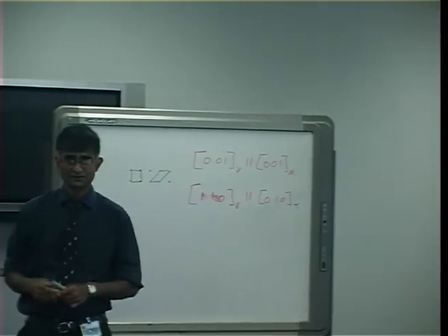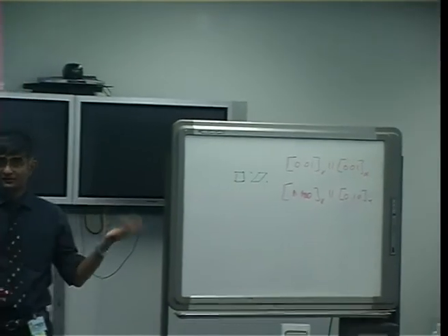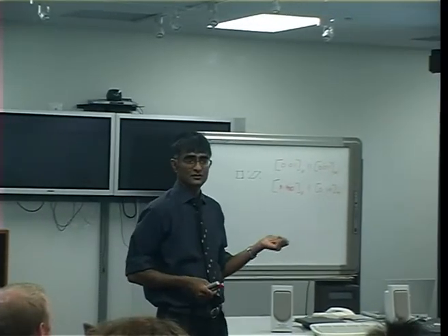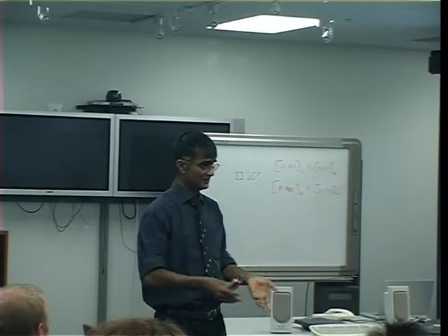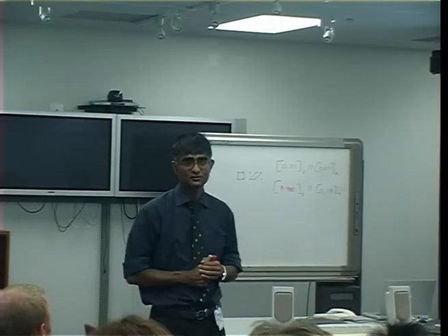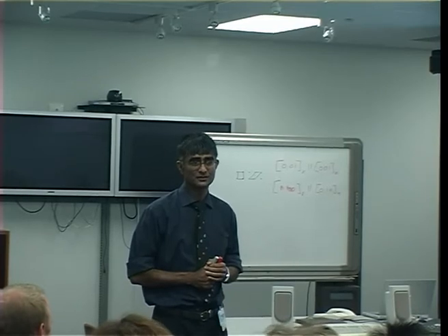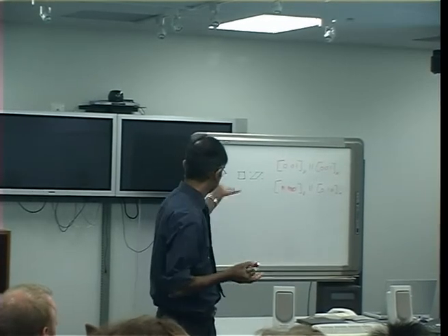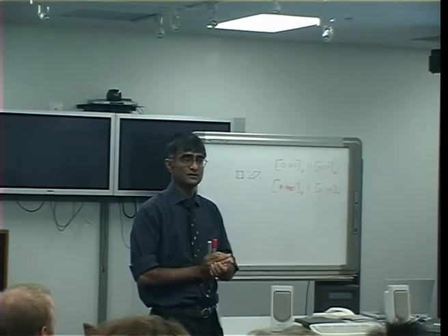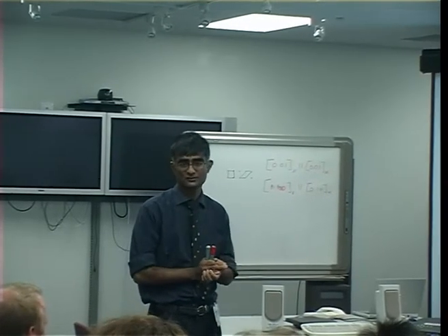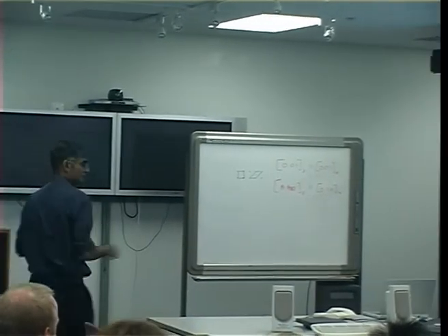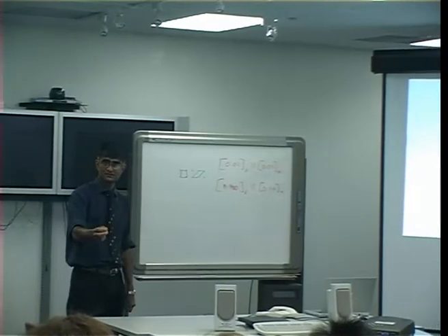So it seems as if we predicted the orientation relationship, but of course this is not what we observe experimentally. So even though Bain has identified the best deformation which would convert austenite into ferrite, it's predicting the wrong orientation relationship. Okay. So we don't have those directions parallel when we measure the orientation. It's roughly the close-packed planes being parallel and roughly the close-packed directions being parallel. So there's something missing from this. So this is yet a fourth inconsistency we have.